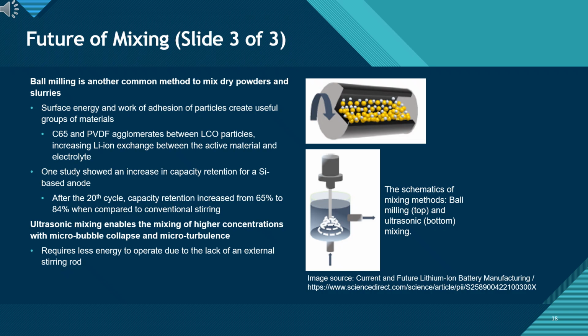Ultrasonic mixing, shown at the bottom, uses microbubble collapse and microturbulence to disperse materials effectively, even at high solid concentrations. Because it does not rely on a mechanical stirring rod, it consumes less energy and offers strong potential for high-viscosity, next-generation slurries. Overall, these advanced techniques enhance homogeneity, improve electrode utilization, and improve long-term cycling performance.